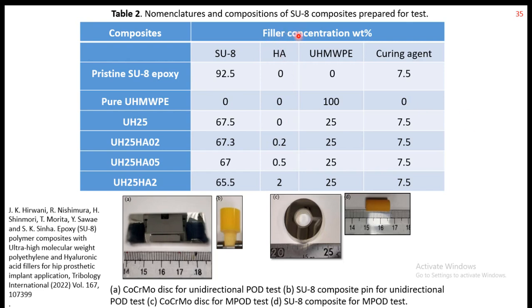So we took SU-8, and into it we added UHMWPE particles at different weight percentages, and we also added HA, hyaluronic acid, as another filler. HA acts as a lubricant in our natural synovial fluid, so this can become part of the composite material. A curing agent was also used because SU-8 is an epoxy and requires a hardening agent to start the hardening process.